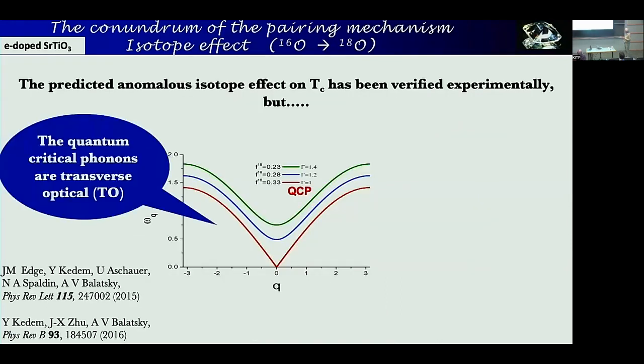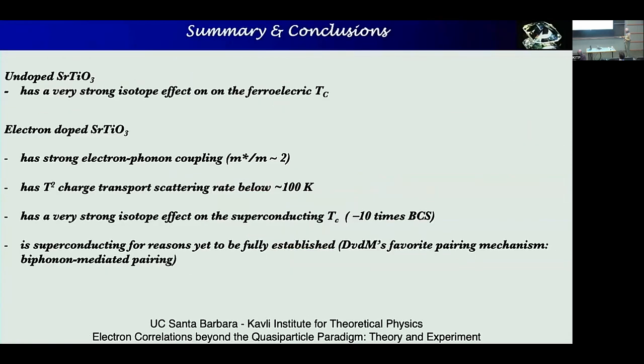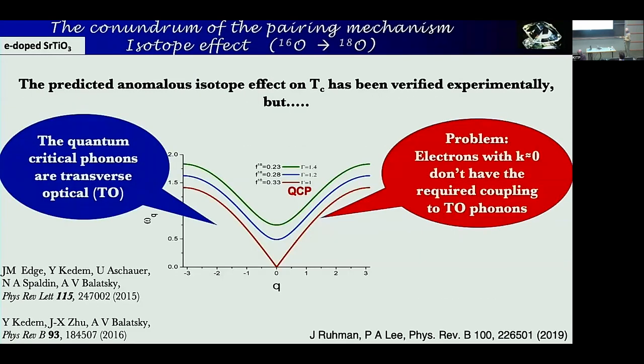Namely, as I already said, those phonons that you're coupling to here, especially near the zone center, are transverse optical phonons, and those phonons don't couple to your electrons, as was pointed out by Ruhman and Lee. So actually, it was the right prediction for the effect that was confirmed by three different groups. But there's something not quite right about the assumption that these phonons couple to electrons in the first place.